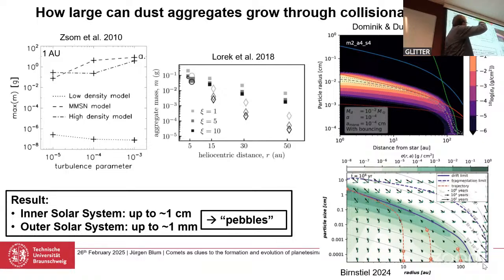We could show we can grow in the inner part of the protoplanetary disk, again, into the gram region, so centimeter particles, in the outer protoplanetary disk into the milligram region, millimeters. And this is why I wrote here, outer solar system up to millimeters is what we do physically understand. And others have followed. So Dominik and Dullemond reach, well, slightly smaller sizes to Birnstiel with his model that builds a lot on our physical results from the experiments, also ends up at centimeter in the inner protoplanetary disk and millimeters in the outer disk.